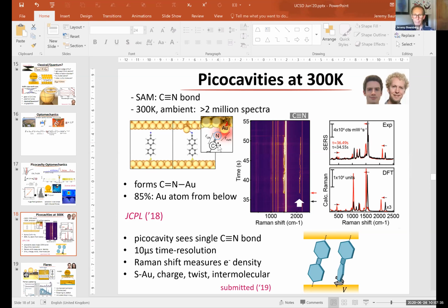Yeah, that's exactly what happens. So in fact, what you can really do is you can measure directly the electron density in this bond as a function of time. We in fact have something like 0.02 of electron resolution inside these bonds now from this. So that's sort of what's in here, but we're doing more of it at the moment because now we can fit the DFT spectrum through the whole molecule. So what we can do is reconstruct the whole system. But yes, exactly right. Essentially, as the gold atom becomes close, it steals electron density from the CN bond into this coordination bond here. And that's what you're very directly seeing here.